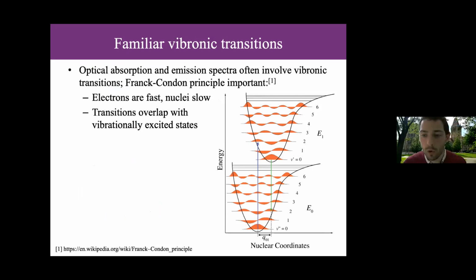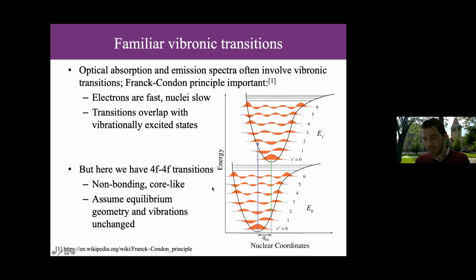Vibronic transitions, you'll know from the Franck-Condon principle, where you have an absorption and you go a vertical transition, you go straight up and you don't change nuclear coordinates, and then you have some vibrational relaxation and then emission, if you're going to be, fluorescence. And this is the Stokes shift. But we don't have that in this case because we're doing 4f transitions, which means that the geometry is not really altered by making the electronic transition because the electrons are non-bonding. And so we assume that the changes in geometry are negligible and that the vibrations of the ground and excited states are all the same.